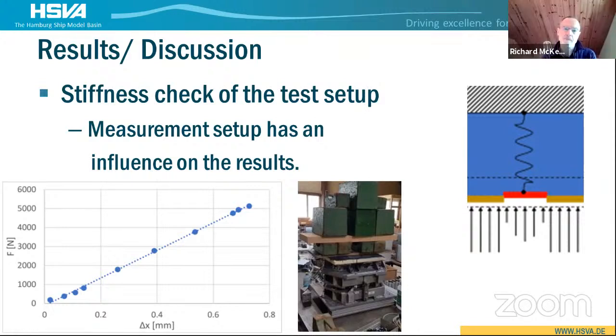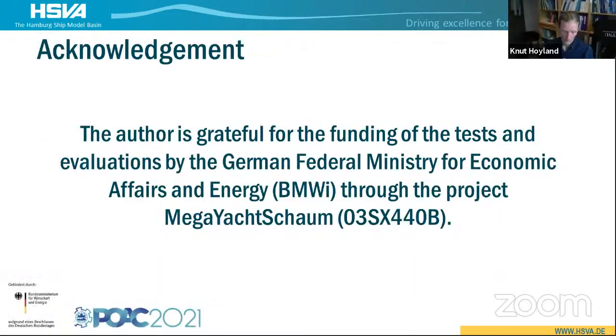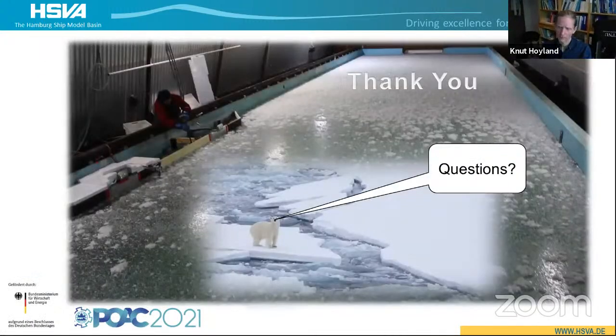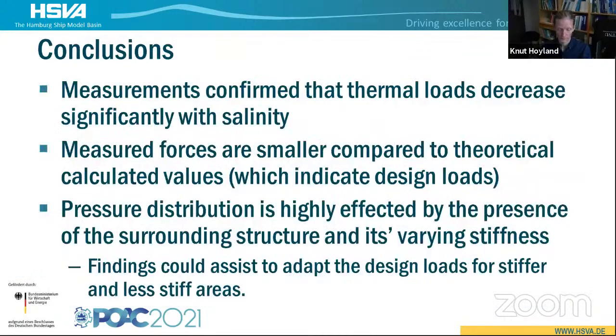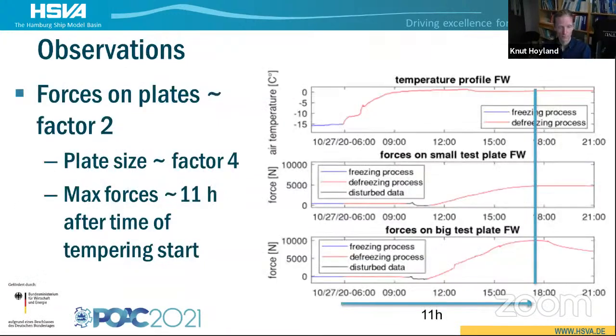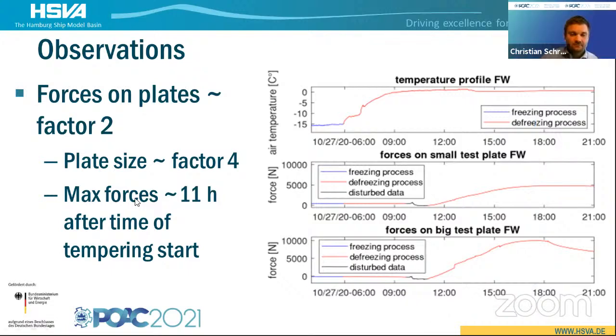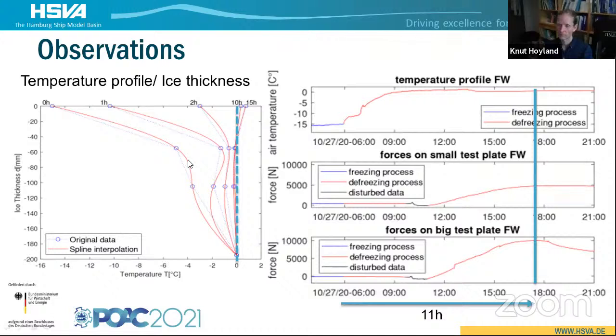Thanks. I have a comment on the measured loads. You only had 15 degrees of increase. In ISO and many papers, they often find the worst case, where they measured 25-30 degrees increase in a day. So it could be that if you manage to increase 25 degrees in the 15, you will get higher forces. Yes, that's an explanation. I mean, you don't really have the worst case with only 15 degrees of increase.